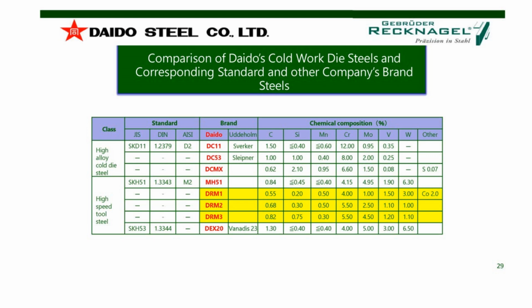The situation with the carbide building elements is a little bit different. DRM1 has a little bit more chromium and tungsten, with 3%. And DRM1, as I told you, is a mix between HSS and hot work tool steel. It also has a content of cobalt. That means that hardness at elevated temperature is higher.